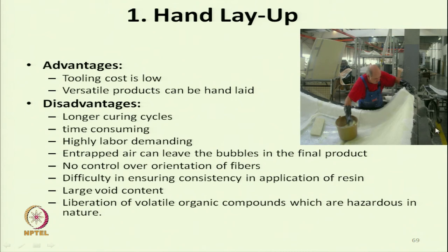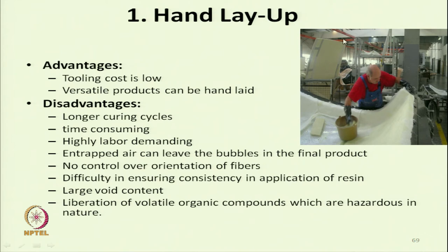Glass nonwoven fabrics can be used, but it is difficult to ensure consistency in application of resin because it is done manually — resin concentration at different places may differ. Large void content due to air bubbles affects the quality. Most importantly, the process is open, so liberation of volatile organic compounds may be harmful for human health. However, the advantage is that it is a simple process.